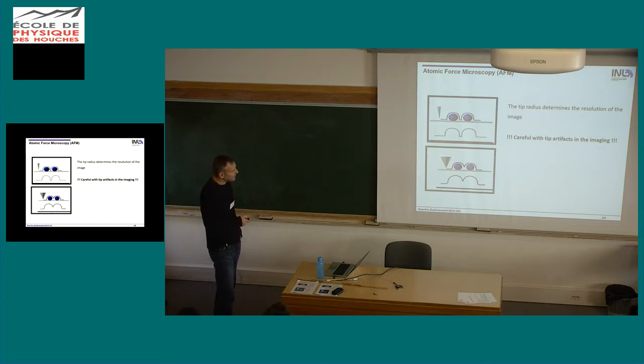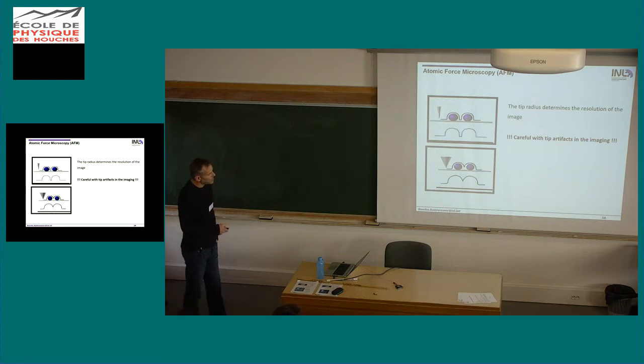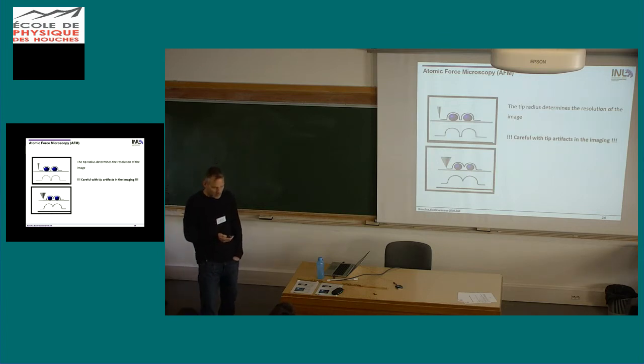But if you have a tip that's not so sharp, then you might not even get in between the two, and you will just get this kind of shape. So whatever you see here, you don't really know what you have, because normally you also don't exactly know how your tip looks. So the tip is also to some extent an unknown in your measurement.